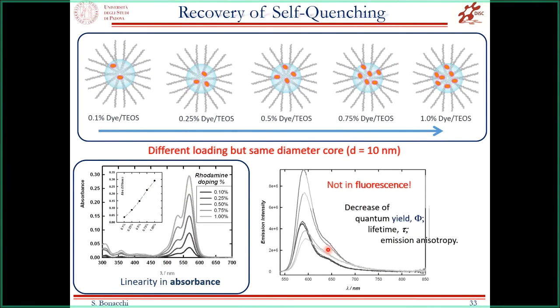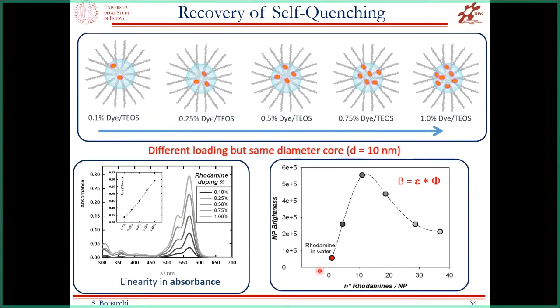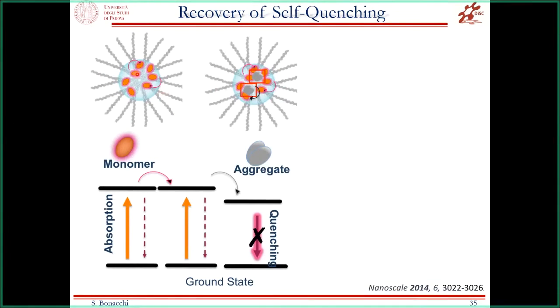But as soon as you look at the emission, and in particular the emission of the nanoparticles, their lifetime, and also the emission anisotropy, we observe that there is an increase in the brightness of the system up to 10 rhodamines per nanoparticle, and then the brightness dramatically decreases. And we wondered why this happened. Basically, we discovered that inside our silica core there is very fast energy transfer among different active luminescent rhodamines.